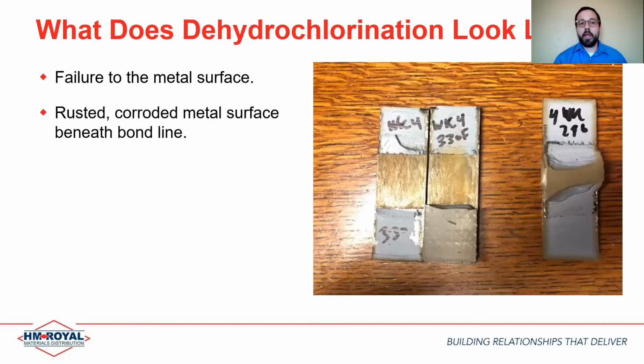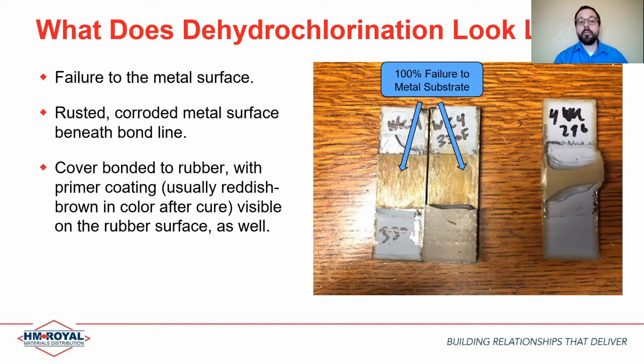So what does this look like in the real world? Basically, we'd be looking at a failure to the metal or substrate surface that we're trying to bond to. In this case, we have metal components, and you'll see a lot of corrosion beneath the bond line as a result of exposure to elevated temperature with systems containing chlorinated rubber. On the left side, you see 100% failure to the metal substrate, which is inevitable over time. We have the cover coat and primer bonded to the rubber half of the component, but a failure to the metal surface. We can also see on the rubber half that the primer coating is intact. As these phenolic primers tend to turn a reddish brown color at curing, it's easy to identify the difference between the black cover coat and the red-brown primer coat.